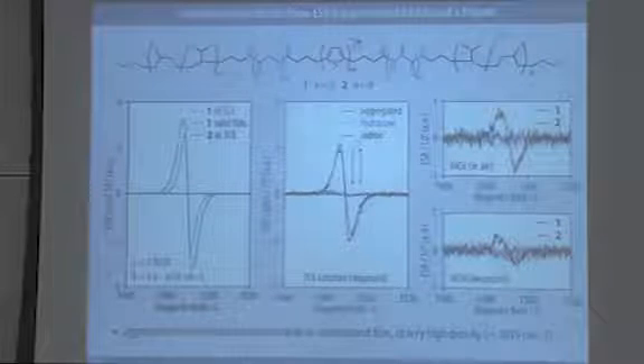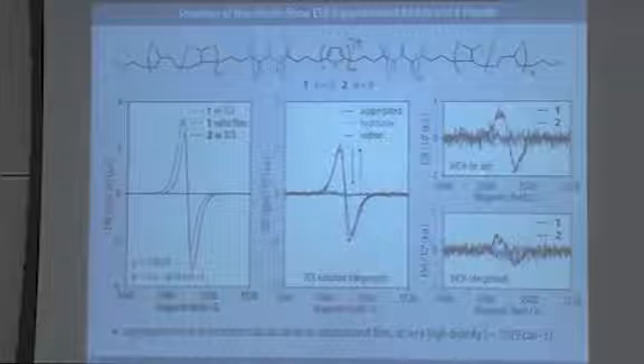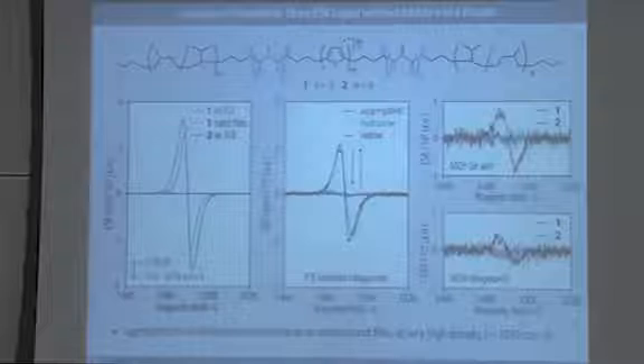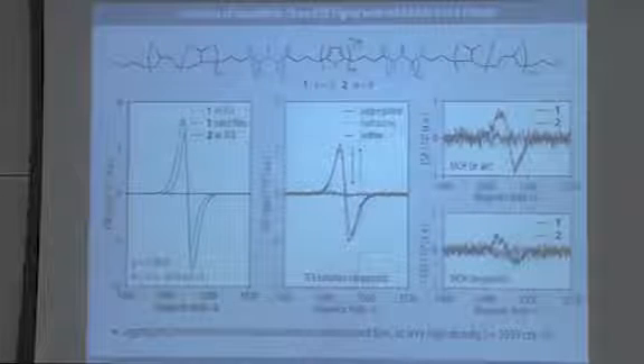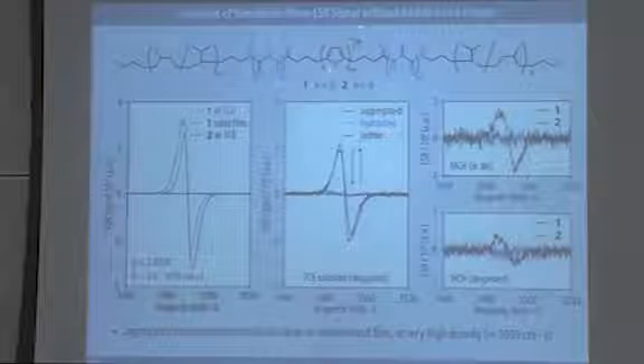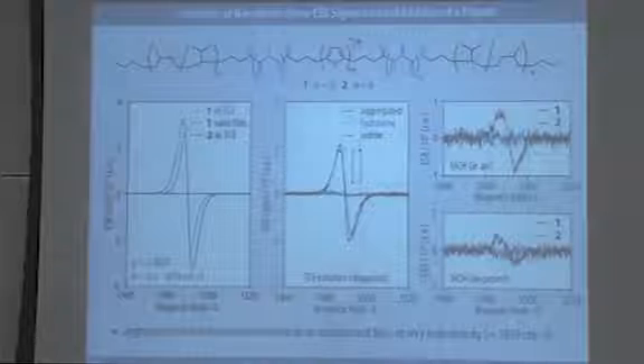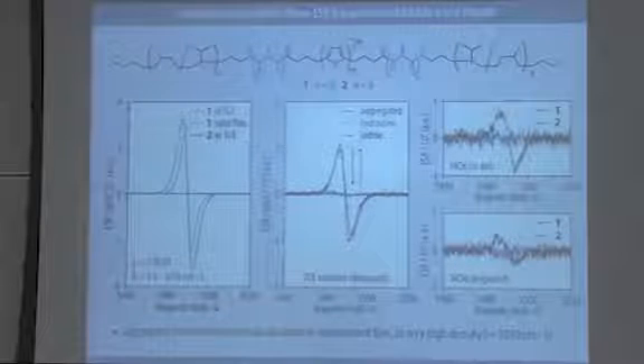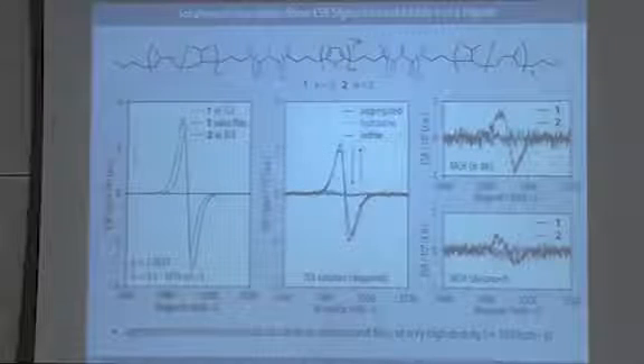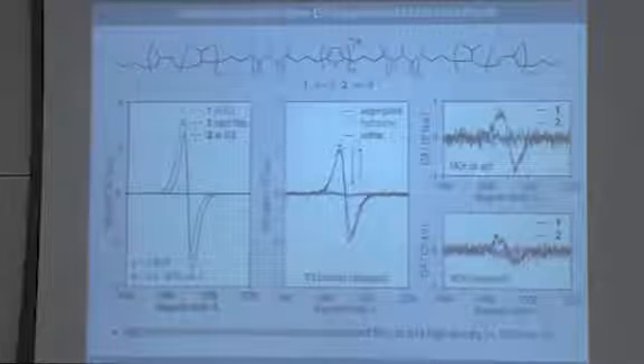16 per cubic centimeter. Now, if you consider the fact that probably the polymer part and the oligopeptide part are innocuous, so it's only the quarterthiophenes that are responsible for that radical cation formation, this actually translates into a spin density on the order of 10 to the 19 in the quarterthiophene part, which is 2 to 3 orders, well, actually 3 orders of magnitude higher than what is observed for polythiophene materials under similar conditions. Again, the ESR signal can be quenched with a reductant. It can be